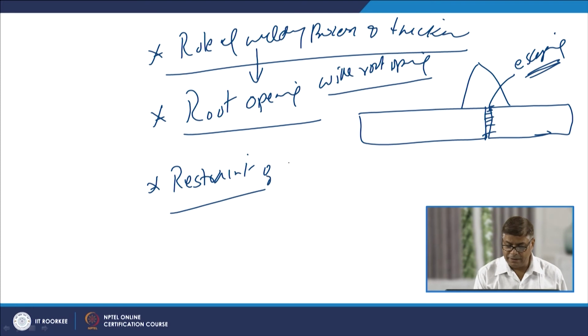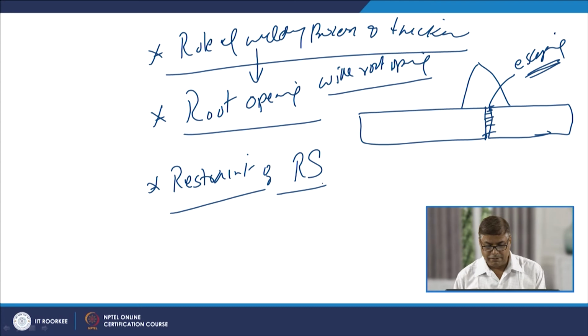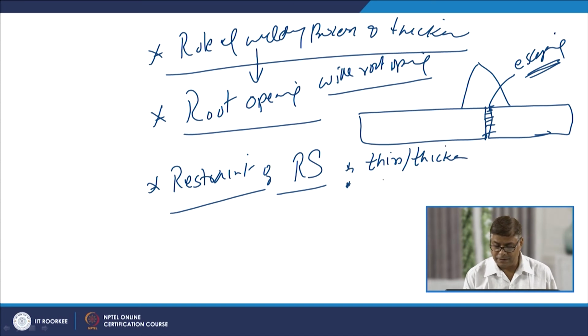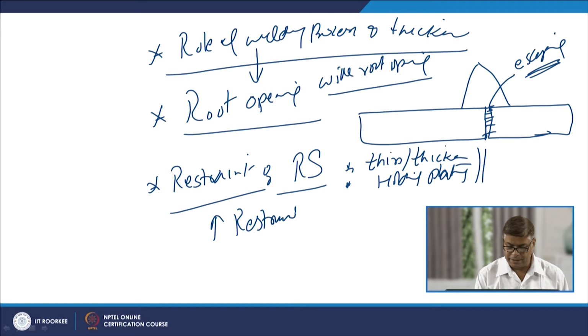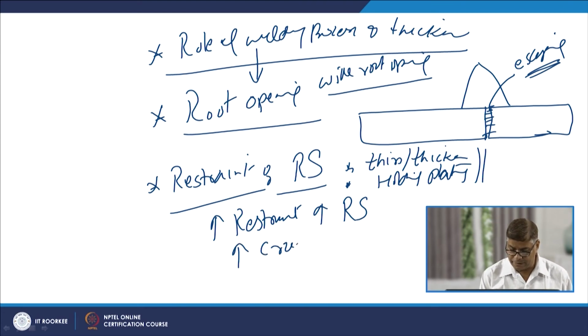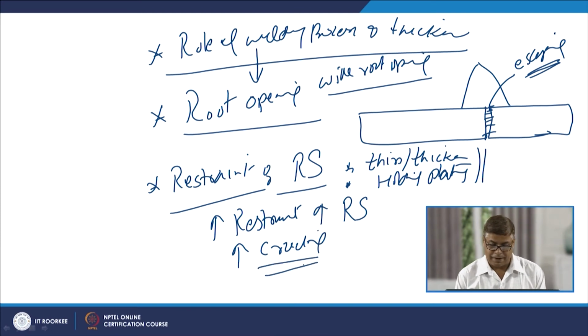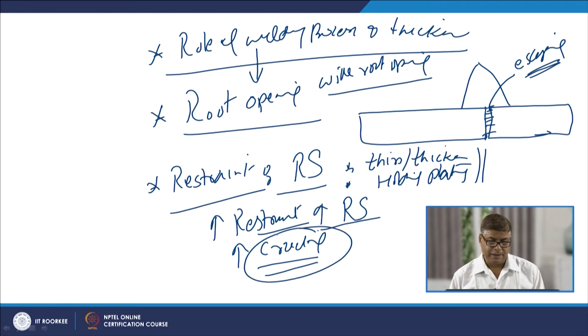Joint restraint directly governs the kind of residual stresses which will be developed during the welding, which in turn will depend upon a number of fabrication conditions, including the thickness of the sheet and the kind of holding of the plates during the welding. So, high restraint during the welding will increase the residual stress development, which in turn will promote the cracking tendency. So, efforts are made to hold the plates in such a way that the degree of restraint during the welding is reduced, so that the associated tensile residual stress magnitude can be reduced in order to reduce the cracking tendency of the galvanized steel weld joints.